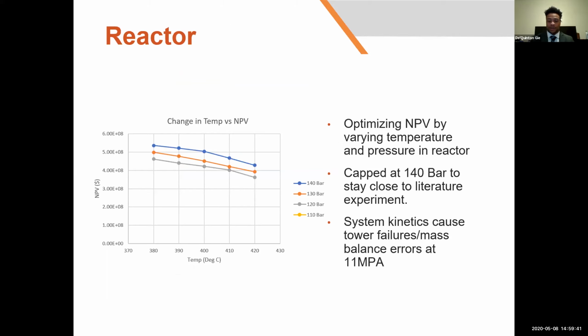So for the reactor, the one optimization we did do was around temperature and pressure. As you can see, we only did between 110 bar and 140 bar. We attempted to stay true to the literature by not straying to any pressures that it had not tried itself. And so we capped the system at 140 bar, which as you can see was the most optimal. And the line for 110 bar was missing due to the mass balance errors created by an error in kinetics.